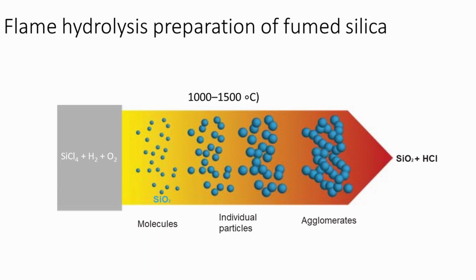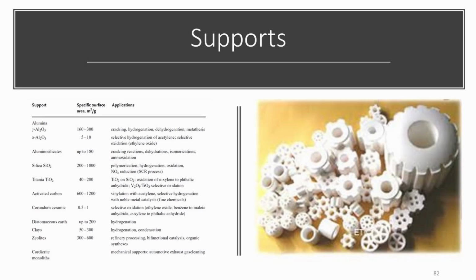Different types of oxide can be produced. It can be silicon oxide, aluminum oxide, titanium or zirconium oxide. One of the oldest examples is the so-called Aerosil process, which is based on a silicon tetrachloride precursor. This precursor is converted into silicon dioxide, typically at 1000 degrees, and it reacts with water that is formed in situ by reaction between hydrogen and oxygen. Alumina is a very relevant catalyst support, as the high surface area gamma or eta phases, as well as the crystalline alpha alumina corundum phase.